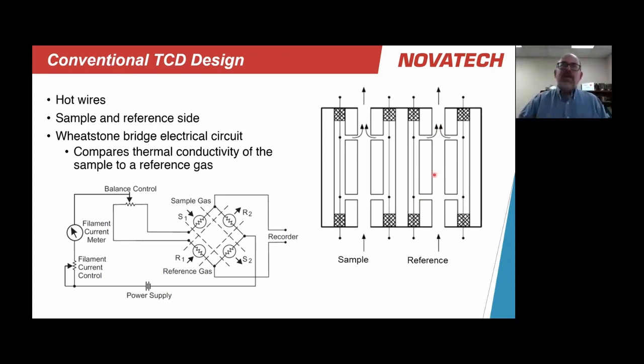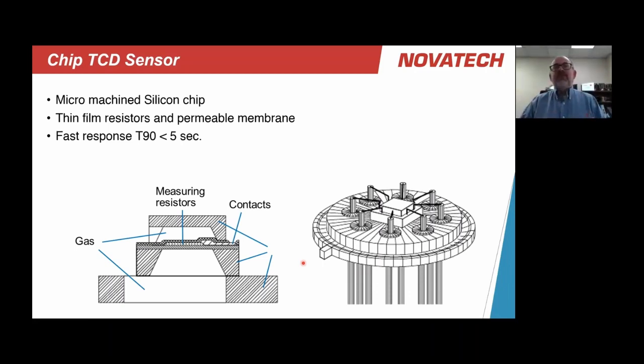And it has to be different, of course. And we compare how much heat is taken away on the sample side versus how much is taken away on the reference side. These are connected in what's known as a Wheatstone bridge, and that allows us to continuously compare the change in resistance as we take away heat from one side versus the other. The way the sensor can be arranged varies from manufacturer to manufacturer. They can be micro-machined directly onto a silicon chip, which has tremendous advantages in terms of speed of response in an analyzer. But of course, for applications where maybe we have corrosive substances, we would probably use the more traditional sensor where we can actually protect the wire elements from the corrosive nature of the gas.